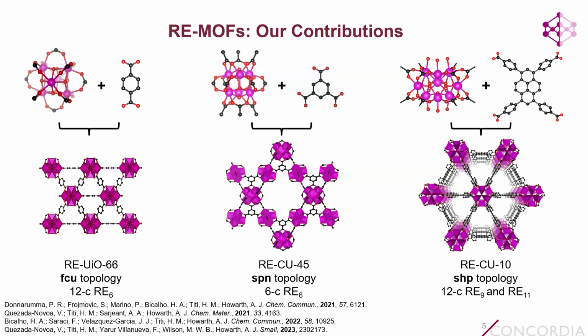We've also shown that you can make rare earth analogs of the well-known zirconium-based MOF called MOF 808. So we call this MOF rare earth CU45, where CU stands for Concordia University. This has these 6 connected hexanuclear cluster nodes bridged by the benzene tricarboxylate linker and the overall SPN topology.